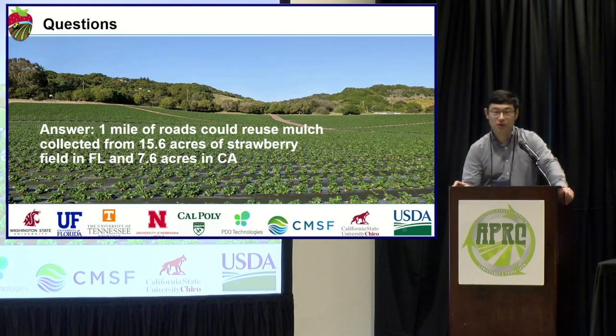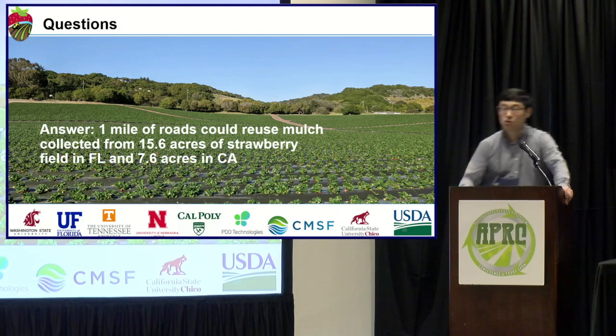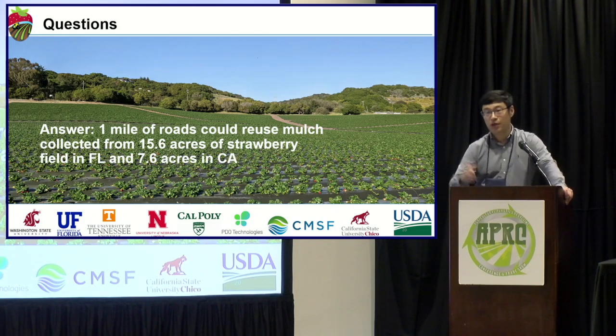That's a good point. For the urban heat island, I don't think there's much difference. Asphalt pavement is black and the mulch is black, so color-wise there's not that much difference. I don't think it will affect the urban heat island issues. Does that answer your question? And also, roughly, we put 3% by weight of the binder, and the binder is 5% by weight of the mix. So roughly we put 0.15% of the total mix. It's a small amount, and that makes some impact for the performance, but not that much.